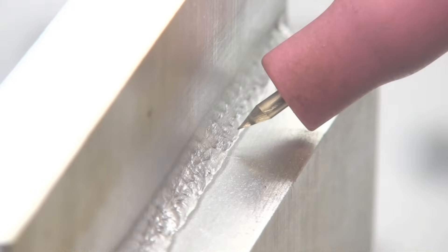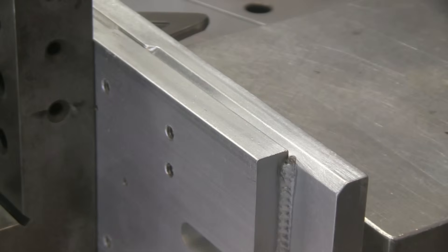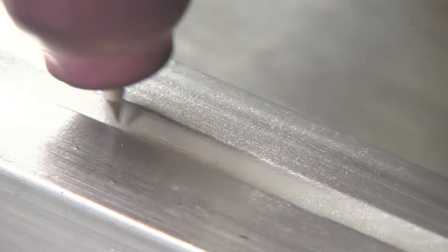And this is after wire brushing, but decent looking weld, and it's penetrated really nicely. It does have a little pore there actually, so you can have that on AC or on DC, but the penetration of that weld is way more than you would get on AC.